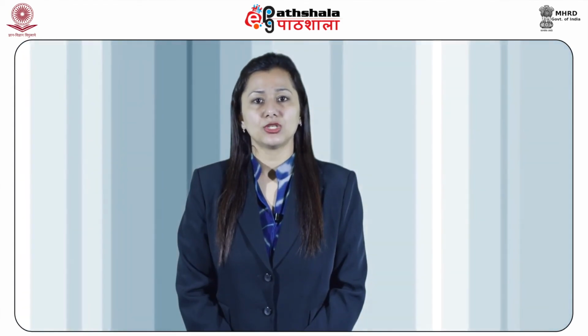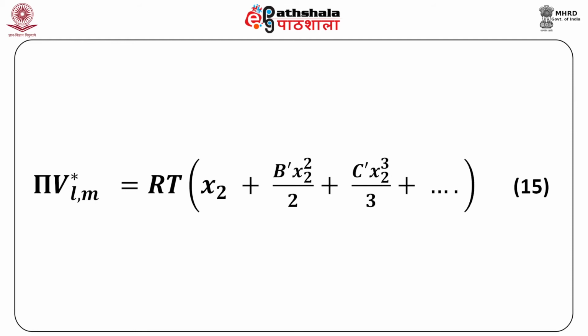And thus expression 8 can be expressed as pi V star Lm equals to RT into chi 2 plus B prime chi 2 square by 2 plus C prime chi 2 cube by 3 plus so on, as our equation 15, where B prime is the second virial coefficient, C prime is the third virial coefficient.